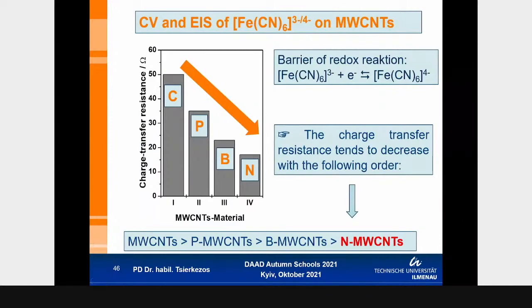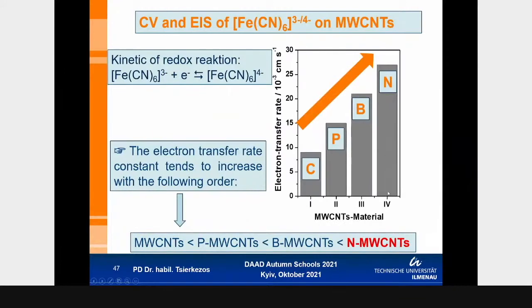So once more in a histogram, the results: you can see that upon doping from pristine to phosphorus, boron, and nitrogen, the barrier of the redox reaction decreases, which means that the charge transfer increases, and which means that the kinetics of the system increases from the pristine to the nitrogen.